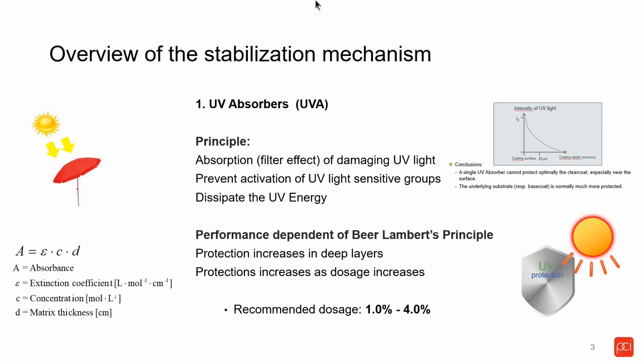That is why our recommended dosage is between 1% and 4%. 1% will be a standard dosage for a pigmented system at about 2 mils film thickness. And 4% will also be the recommended dosage if you have a clear system and you need quite good absorbance at 2 mils. So again, the dosage is always proportionally related to the thickness.